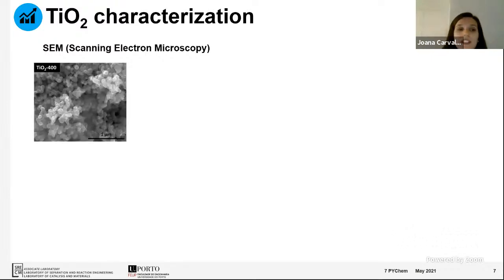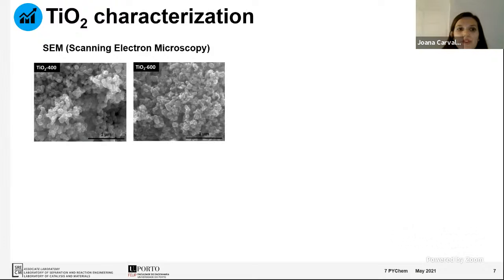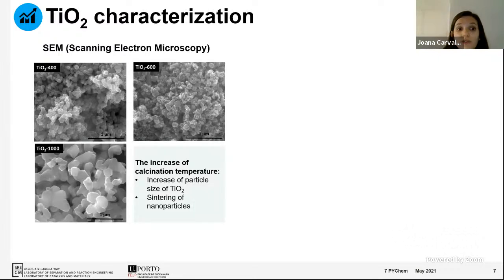This image represents the material calcined at 400 degrees. It is visible that this material has small particles with a spherical form. With an increase of temperature to 600 degrees, it is visible that the particle size increases and the shape is different. And when you look at the same image of the material calcined at 1000 degrees, it is obvious that the particle size increased and the shape is very different compared with the first one.